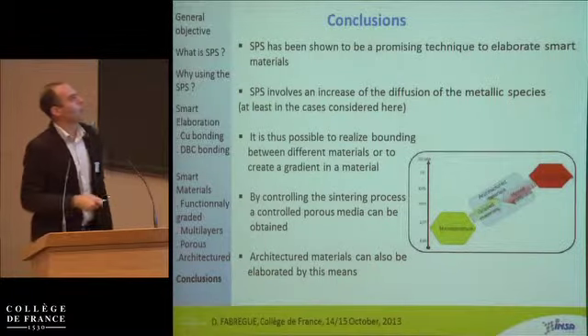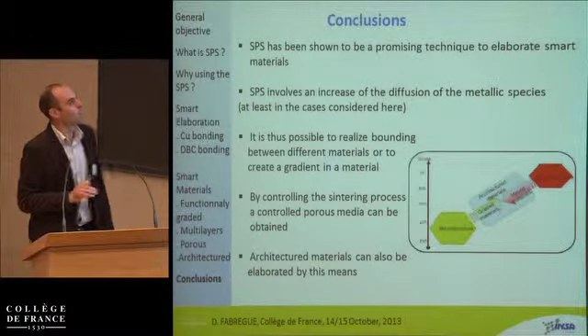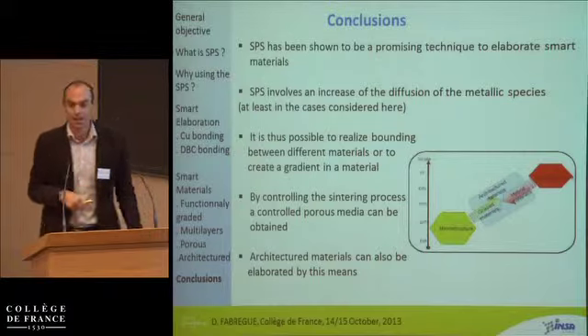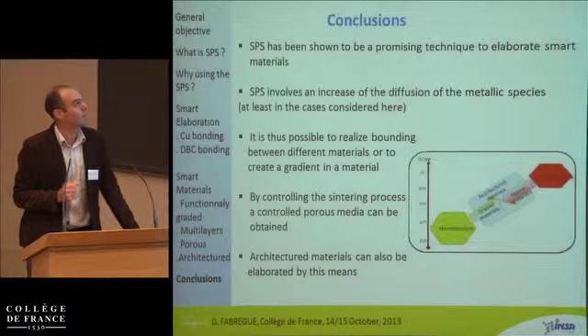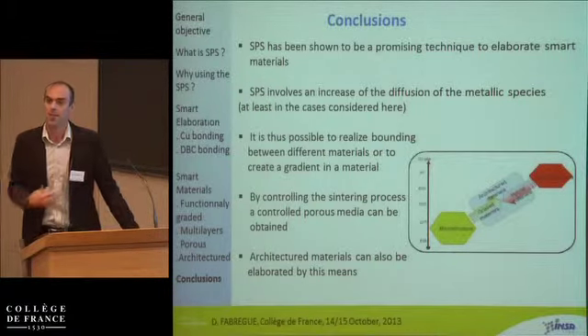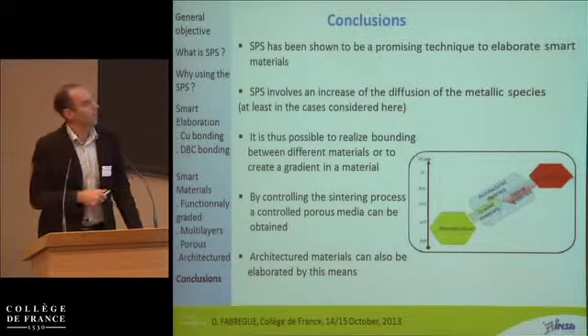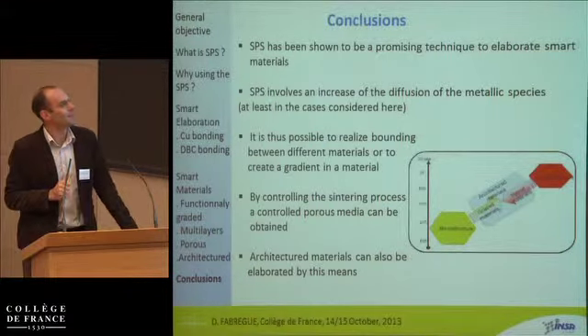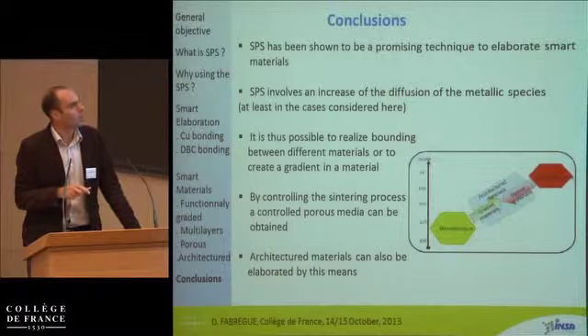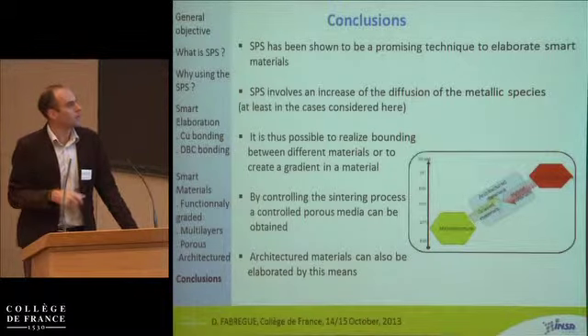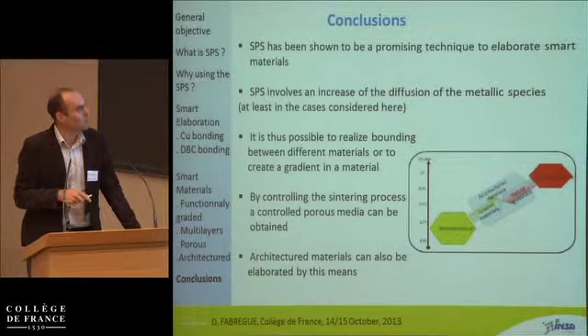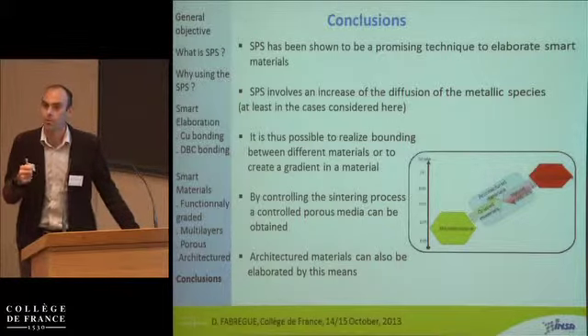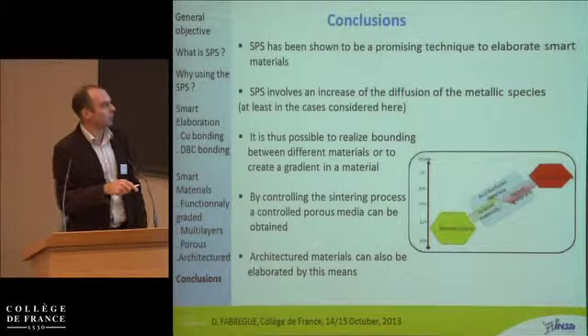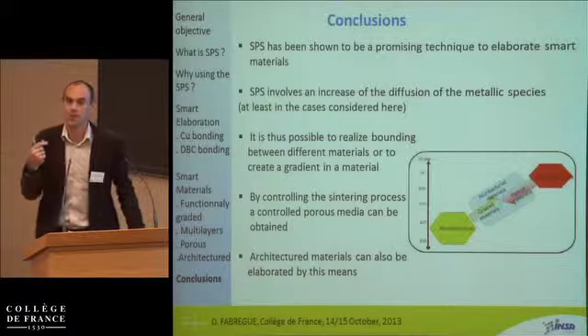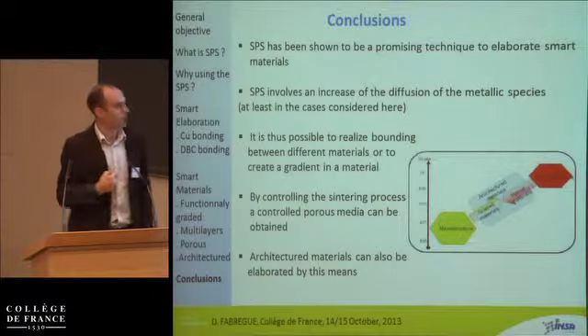So here are the conclusions. I hope I showed you that SPS is a promising technique to elaborate smart materials. As I showed you, it enhanced diffusion of the metallic phases, at least in the case considered here. We can do bonding at low temperature for a short time. You can control the process in order to get controlled porous materials, and you can also have architectured materials if you think a little bit about what you want to have.